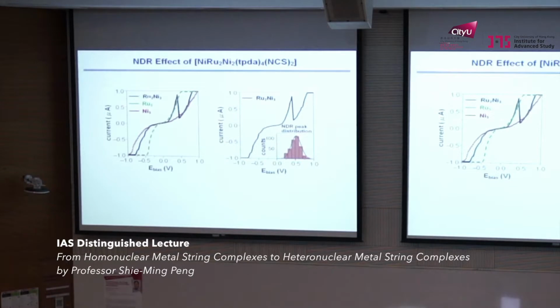But for the ruthenium-nickel metal string, the black line is the IV curve of the heteronuclear metal string. It shows a very interesting negative differential resistance effect. That means you apply the potential, the current drops, then you increase again. Very interesting, if I put the IV curves of the ruthenium and nickel together, you can see that at some potential this mixed metal string behaves like ruthenium, and at some potential this mixed metal string behaves like nickel. So you can change the mixed metal string between two types, but of course at different potentials.